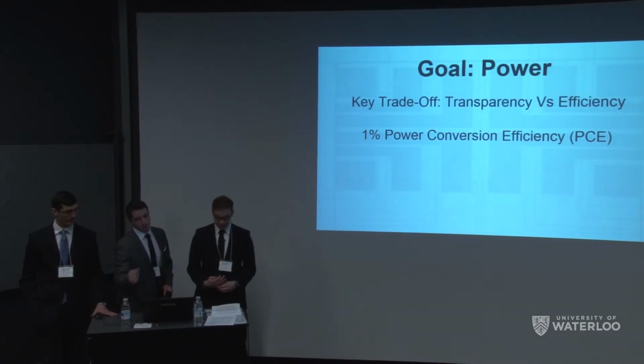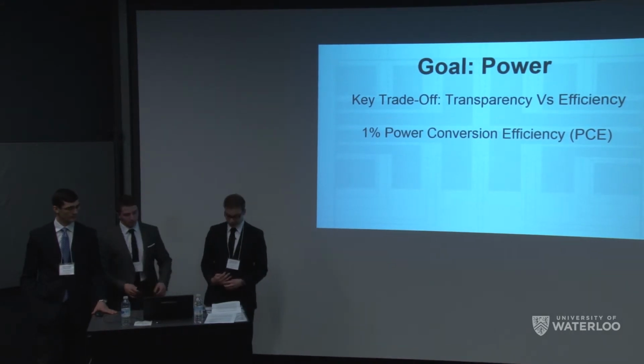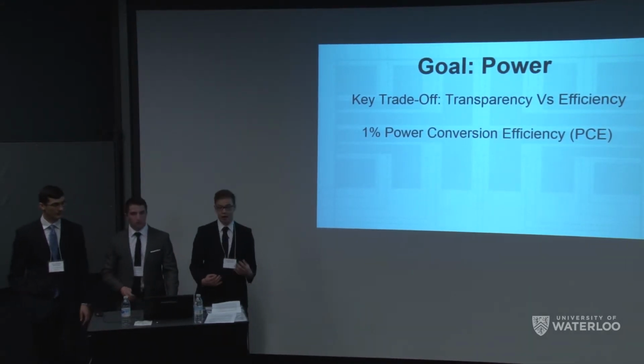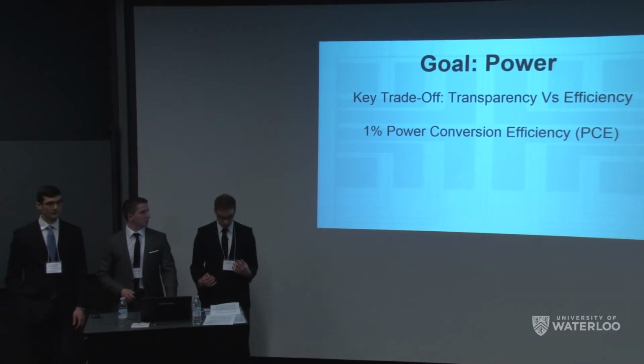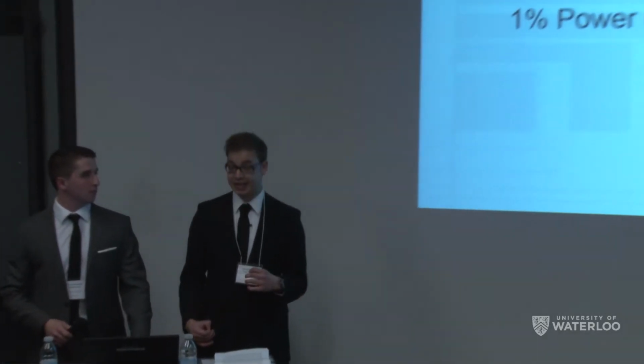Our power goal for this device was to achieve a 1% power conversion efficiency. This would produce about 1 milliwatt of power per centimeter squared at peak solar intensity. Though state-of-the-art organic solar cells could produce as much as 10%, we had to make a design trade-off between transparency and efficiency. Based on the distribution of light in the solar spectrum, we picked a 1% power conversion efficiency.